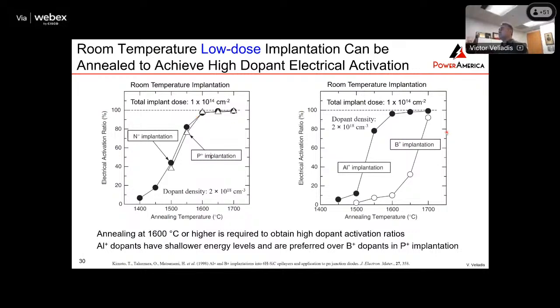And this graph right here shows the electrical activation for P+ implantation for the two available species, the aluminum and the boron. And you can see that if you do room temperature implantation at low dose, if you anneal at about 1700 degrees, the aluminum will activate almost all of the dopants. But in the case of boron, you have to go to higher temperature to get the dopants to activate. So therefore, aluminum is the preferred species for implant for P+.